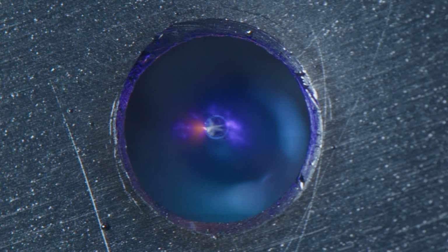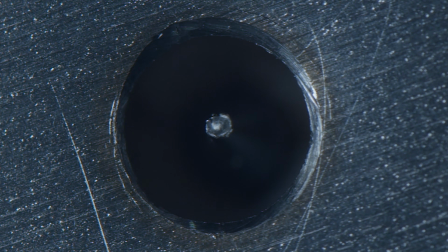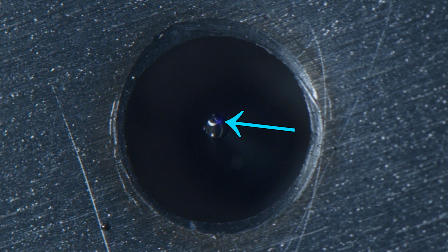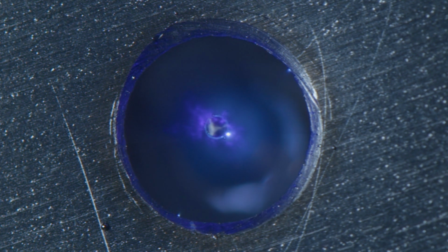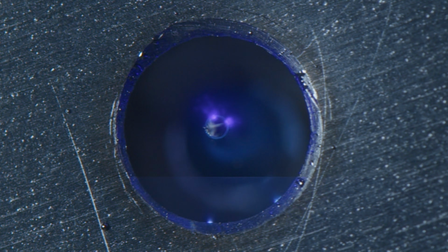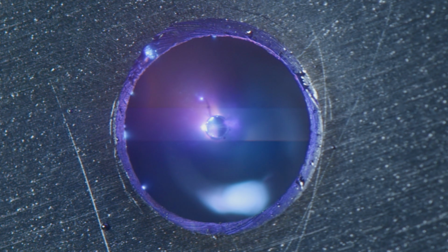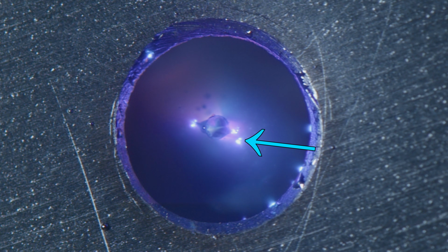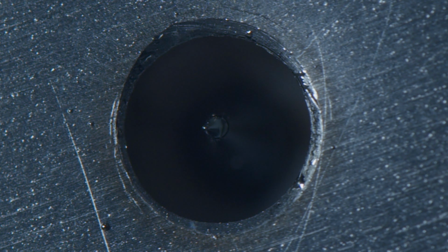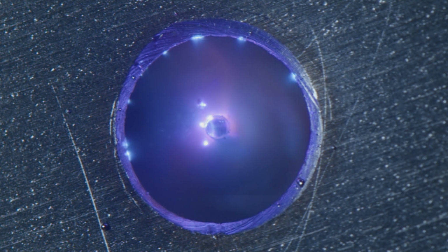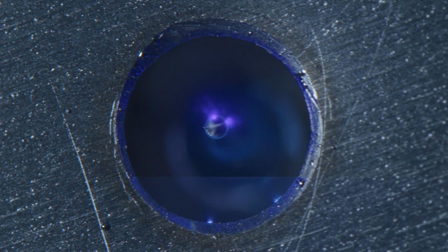To be clear, this isn't working at all. This was an abject failure of a test. But diagnostically, this was huge. First, we can see the liquid metal being pulled towards the extractor, and then we can see some Taylor cones starting to form on the surface. Then there are blasts of plasma erupting from those spots. There are also very obvious droplets shooting around and landing on the electrode. So the process is almost working, but we're generating big droplets instead of controlled ion emission.